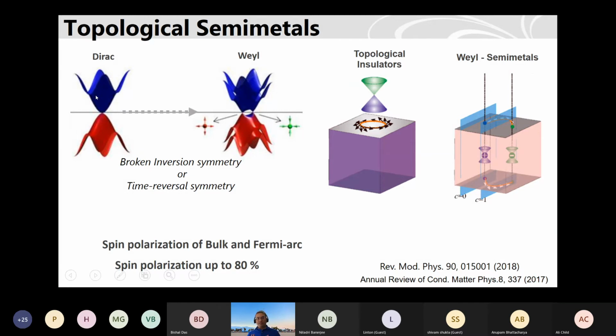If you have a topological insulator, you can apply a magnetic field, and that will also change it. It's a bit high magnetic field of a few Teslas. Then you actually go to the Weyl states like bismuth. In the bismuth selenide and telluride systems, people have shown that experimentally. For the other way around, if you have a Dirac system and you break inversion symmetry and/or time reversal symmetry, you also can go to these Weyl states. So that is a simplified explanation.